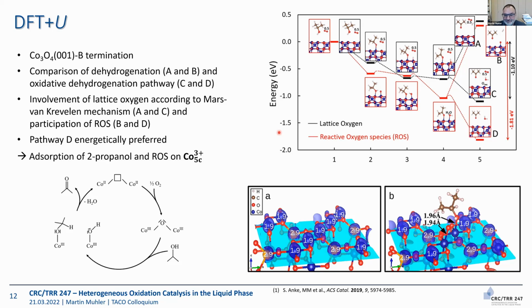And you may have wondered, why did we decide to use spinels and perovskites as oxides? There are much more fancy ones. So one answer to that question is these are more or less simple cubic structures, and that's a major advantage for theory to work on them. That means these calculations can be performed with great care. These are DFT plus U terminations. We take the cubes, the B termination of the 001 facet.